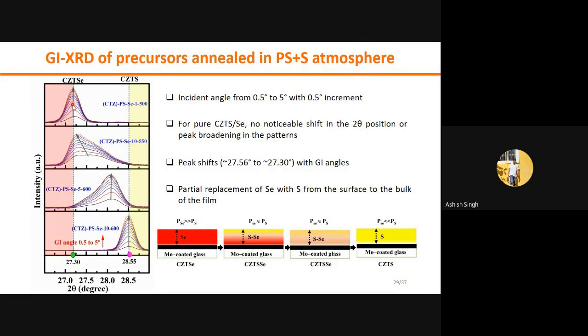For the phase pure CZTSe and CZTS, the sulfur and selenium are homogeneous throughout the sample. In CZTS, sulfur is homogeneously distributed throughout the sample, while in phase pure CZTSe, the selenium is homogeneous throughout the sample. It is important to notice that in the solid solution, from top to bottom, the sulfur and selenium proportion is varying. That means a sulfur-selenium composition gradient happens in this material. This gives you the opportunity to make a graded band gap absorber material, and the absorption will be efficient in this condition.